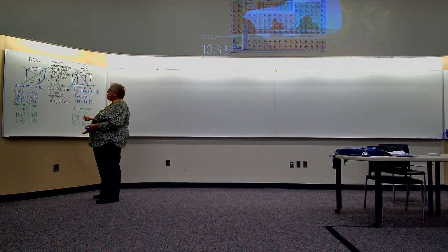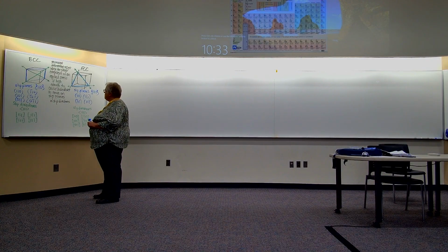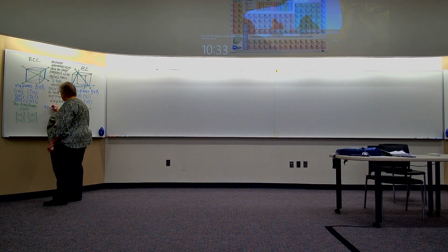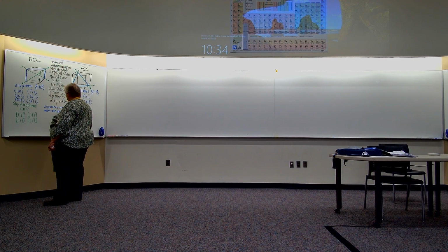So permanent deformation in BCC happens on those planes in those directions. FCC happens on those planes in those directions. Slip planes are those that are most widely spaced.